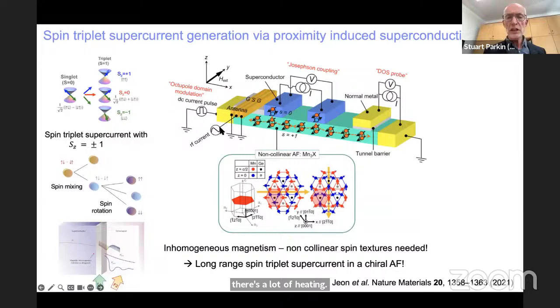I just want to point out that we explored the possibility that this non-collinear spin texture, which Bergeret had predicted is needed for long-range triplet supercurrents to propagate. So this is some work by Kunrock, a postdoc in my group. Now he's back in Korea. And what he was able to show was you could form a Josephson junction between these two blue layers shown here, which we used electron beam lithography to create on top of this green layer, which is this chiral antiferromagnetic structure. And what he found was long-range supercurrents would flow from one blue niobium electrode to the other, even though this system has manganese atoms with huge magnetic moments. A lot of magnetization, but it's in a chiral non-collinear structure. And this, we demonstrated, stabilizes long-range supercurrents consistent with long-range spin triplet superconductivity.